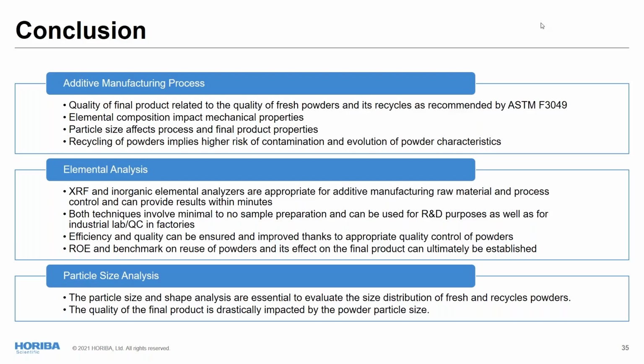Then, as we were discussing at the beginning, the quality of the final product is really related to the quality of the fresh powder and also its recycle, as recommended by the ASTM norm. The elemental composition impacts the mechanical properties. The particle size affects not only the process, but also the properties of the final product. And as we saw along the recycling, we see some evolution of the content and also of the particle size and shape of the sample, which happens due to contamination over the process and to the evolution of the powder